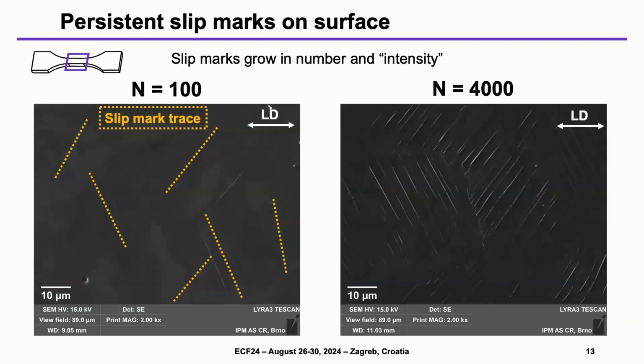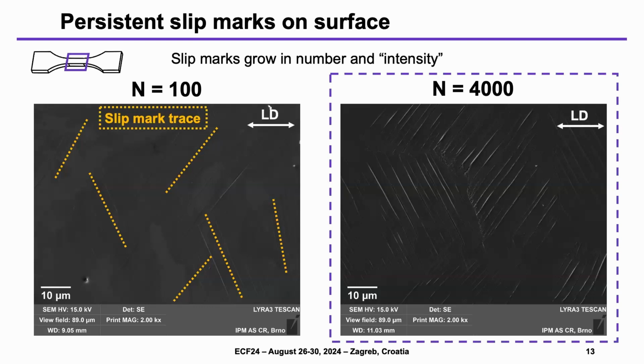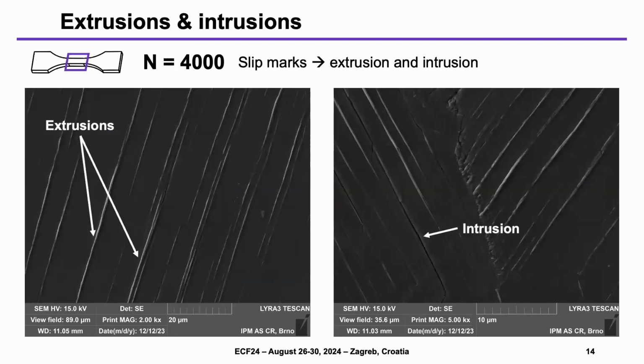Here it's not so easy to see, but there are some slip marks on the surface with different inclination with respect to the loading direction. And this different inclination is likely due to the different grain orientation from region to region of the material. And of course, these slip marks are more visible after 4,000 cycles. And at higher magnification it is also possible to find some, let's say, morphological features of these slip marks.